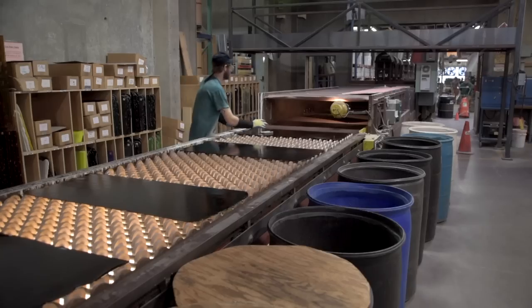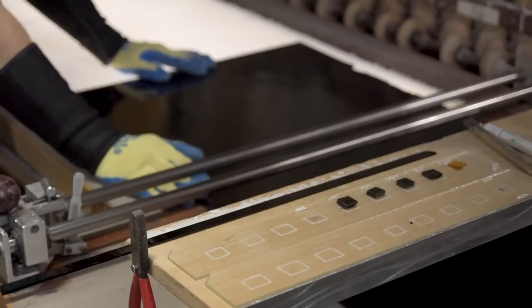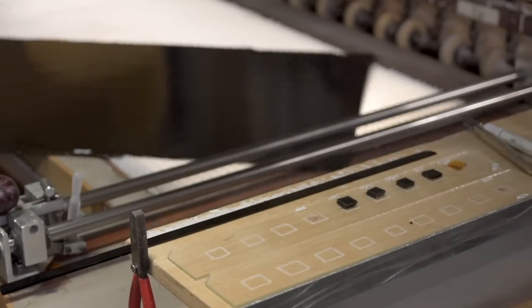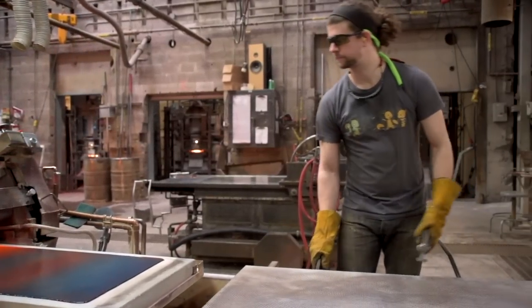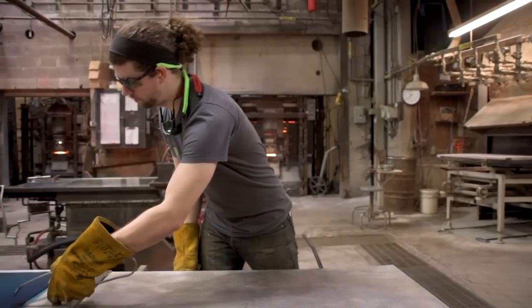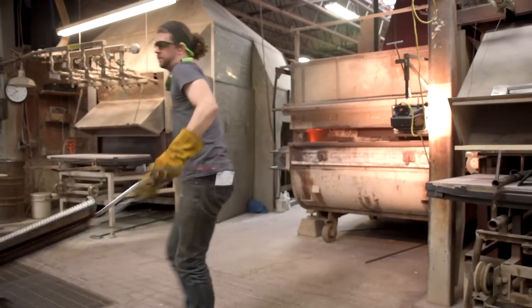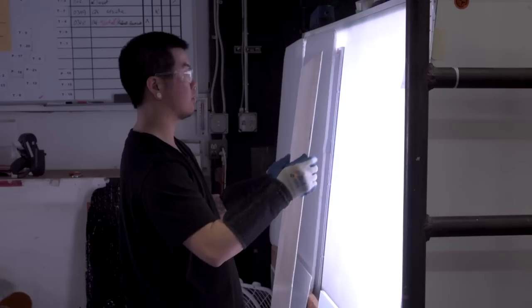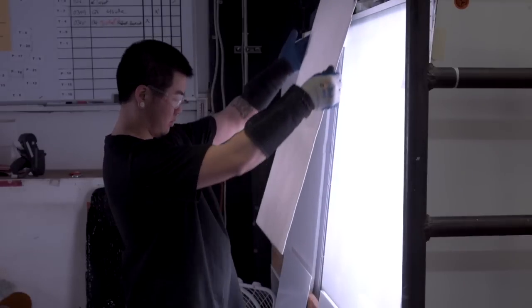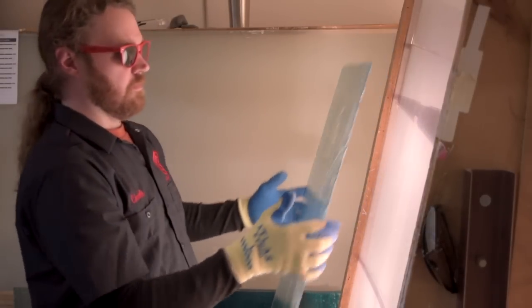My name is Charlie Telleson. I'm currently the quality control supervisor. Today we're averaging about 900 sheets — we'll be trimming into spec and grading each sheet one-on-one. All the glass we receive in QC is delivered to us from the casting department through an annealing layer. It slowly anneals from 1300 down to 300 degrees over 35 minutes. There are a lot of differences between the sheets on a run-to-run basis just because all of our sheets are handmade and formed. Within the quality control department, after the glass has been graded and set aside, we'll hold it here in QC for 24 hours while we review and perform all the compatibility tests on it.